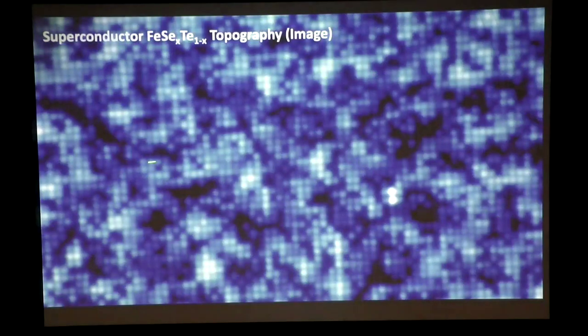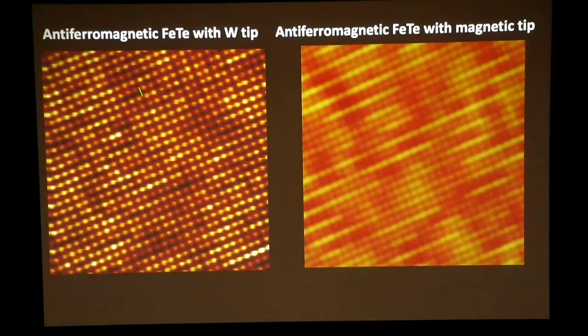Let me show you what happens when you take the same iron selenide and add tellurium. Now the image looks like this. That chemical inhomogeneity, which occurs because of the addition of tellurium, now translates into electronic inhomogeneity. So now if you go to the other end member, iron telluride, FeSe that I showed you before is a superconductor. FeTe is an antiferromagnetic metal. It has a very peculiar kind of antiferromagnetism where you have bicollinear stripes.